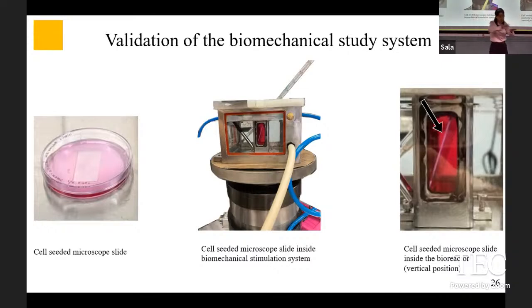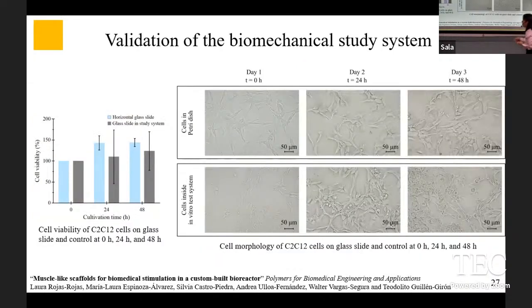And at the same time, we had a microscope slide on the same conditions in a commercial incubator. So what we were expecting was to see if there was any difference between the system that we built and the commercial incubator. There should be none, right? And fortunately for us, that was the result. When we measured the cell viability of the cells on glass, we noticed there was no difference between each other. I mean, you can see a slight difference there, but that's normal for cells. And this result is very important because it means that the in vitro test system is working as a bioreactor.